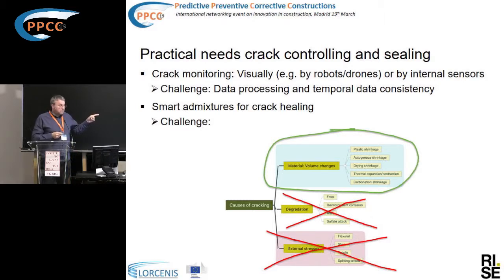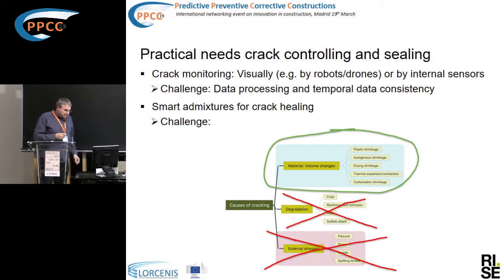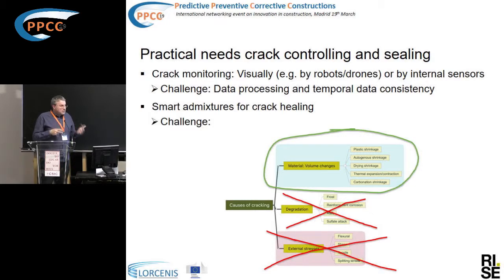When you have ASR and cracking, filling in the crack doesn't help — the concrete will still be damaged. The same is true for reinforcement corrosion. And for cracks caused by external stresses, it is also difficult to regain structural health through crack healing. At the moment, crack healing is more about plugging cracks to prevent ingress of damaging materials, rather than recovering structural performance.